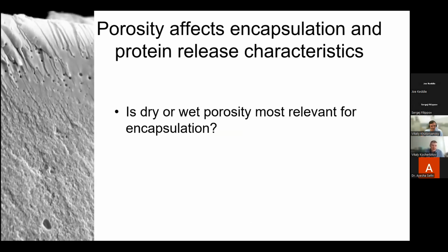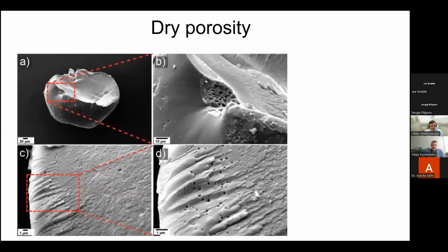You can see that closer to the surface of the microparticle there are no pores, but then we have larger pores, and closer to the center we have a material where we cannot really distinguish what kind of porosity we have, because the pores, if they exist, are very small, but it has a different texture compared to what we have at the surface. Another microscopy slide again illustrates a difference in porosities in different parts of the dry microspheres.